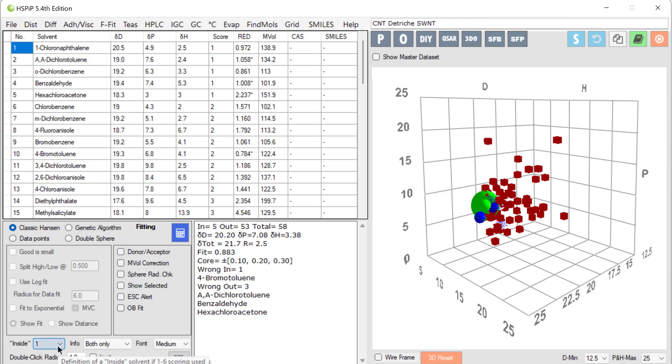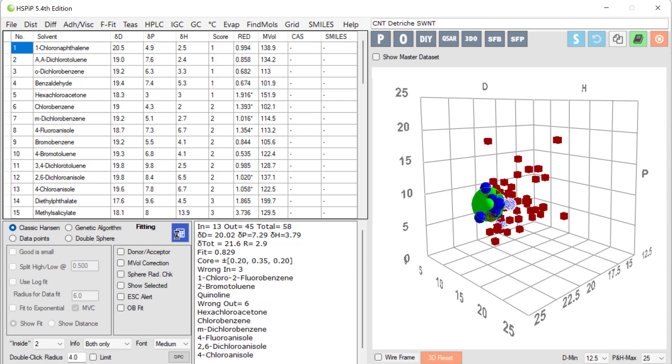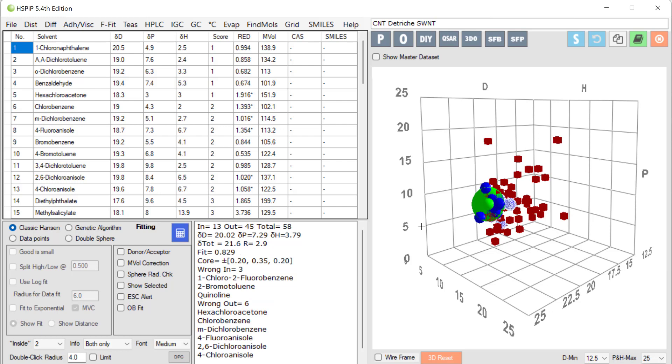We can also say, well, the twos, and I've seen these tubes myself, are not so bad. So let's include those inside. So we can fit now with the ones and twos. And we get a bigger sphere, a larger radius, of course, because we're being more relaxed. But we get approximately the same value.